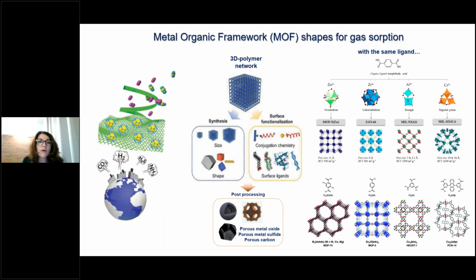Just to give an idea of the flexibility of these materials, metal organic framework are basically composed by metal ions linked with ligands. Here, metal organic framework can assume a 3D polymer network. We can change the size, we can change the shape, just acting on the synthesis procedures. We can functionalize the surface by simply conjugation chemistry approach. And also we can, after use, post-process this metal organic framework to obtain porous metal oxide materials for other or similar applications.